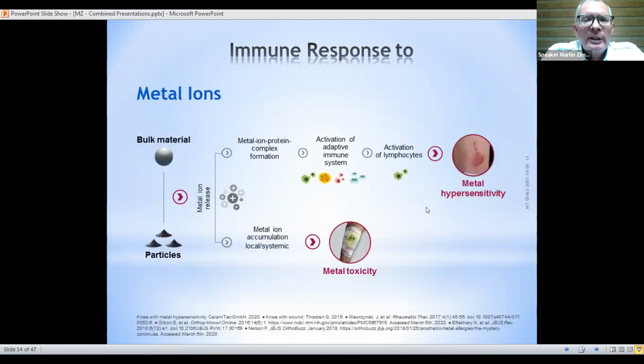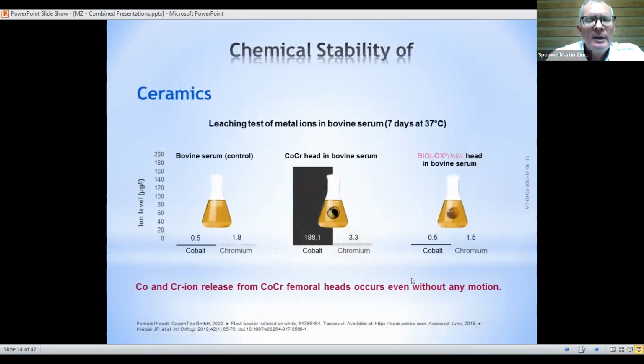Let me go now to another level, metallic ions. The metal ions can come either from the bulk of the material, but also, of course, from the particles of the wear debris. And again, as shown here, what you want to avoid is metal hypersensitivity, or even, in most cases, metal toxicity. To analyze that, we have done a study on the metal or particle release from cobalt chrome ball heads and compared that with a ceramic ball head.